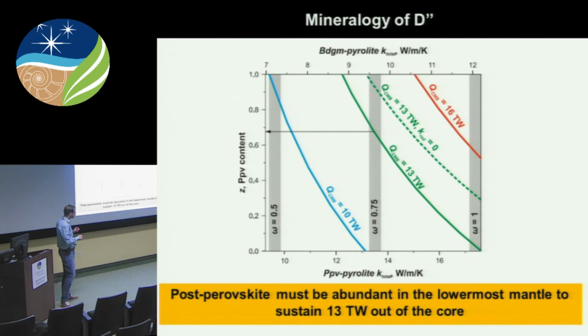This is why I have to introduce this downward correction factor. When omega is 1, basically the correction factor is 0. So omega of 0.75 is a 25% downward correction factor. This omega is more or less consistent with what we know on impurity scatterings in MgSiO3 from theoretical studies. So this may be the value that we would expect from molecular dynamic simulation. Projecting this value on the 13 terawatts curve gives us the 70% amount of postperovskite. And the second part of your question was?